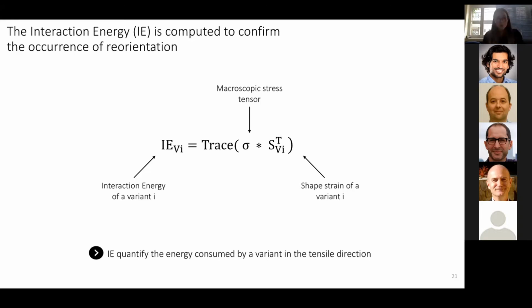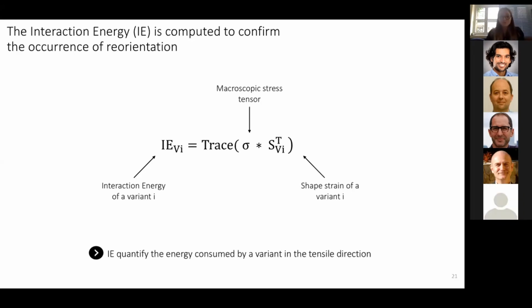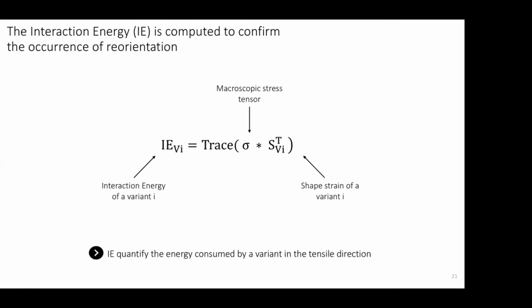And if it works, it can also be very useful to predict the reorientation, because you can compute this value on the martensite before deformation. And if you know the direction of your stress, you can say, okay, I know this variant will be the one that will grow under the effect of deformation. And as you can see, this value depends on the macroscopic stress and also on the shape strain, a value which was already computed.